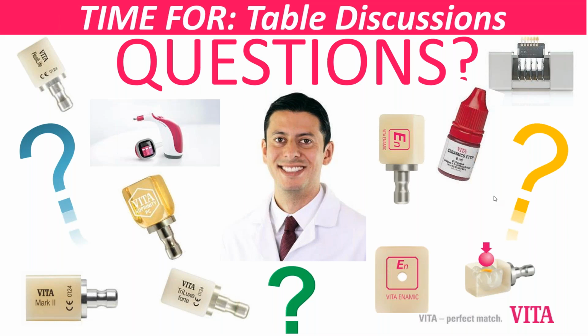Well, yeah. So for hybrid ceramics, let's start from the hybrid ceramics. The publication that I showed last webinar on JPD on bonding to Enamic, we tested 60 seconds, we tested 120 seconds, and the bond strength and the strength of the material was the same. So you could go from 60 to 120, but I wouldn't go more than 2 minutes on the hybrid ceramic, and that would apply as well for the feldspathic ceramics.